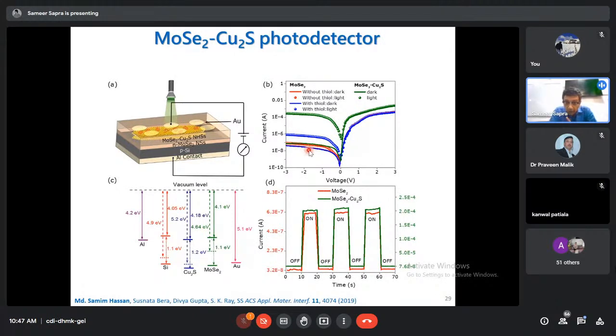But what you see when you make the heterostructure is you have the effect of passivating the defects, so allowing for the passage of charge carriers, and also a natural separation. Okay, and this is typically about 2700, I think, fold increase in the bright to dark current ratios over here. Very, very efficient devices, very, very efficient photodetectors, if you have passivated the defects, and also the fact that you have natural separation because of the type 2 heterointerface.